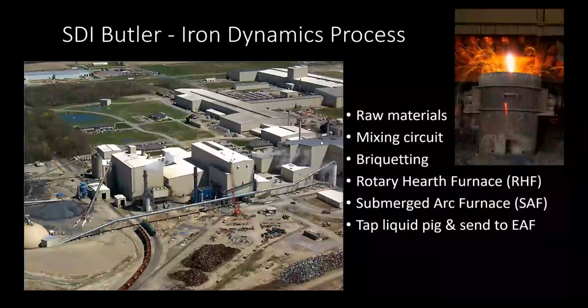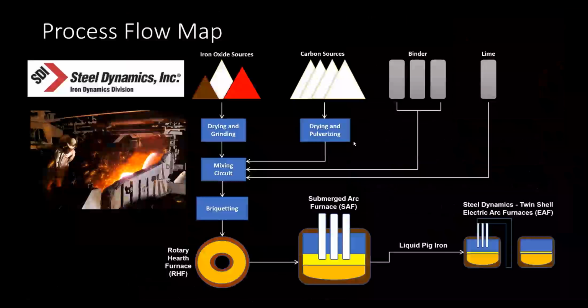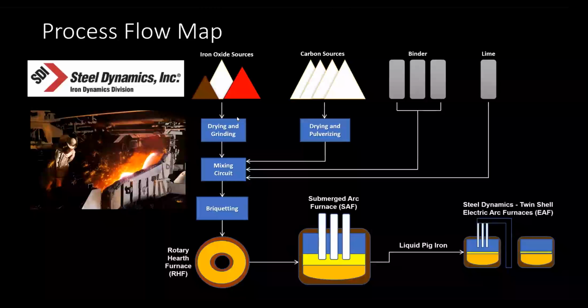For iron dynamics, for the raw materials, we use a mixing circuit, briquetting, rotary hearth furnace (RHF), submerged arc furnace (SAF), and tap liquid pig iron, sending it to our EAF. Our process uses recycled iron ore products, carbon sources, coals, binders, and lime for fluxing.